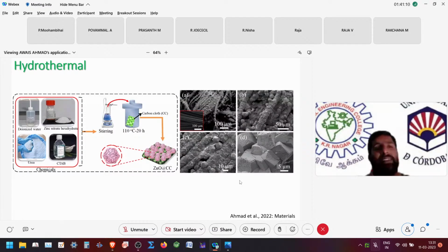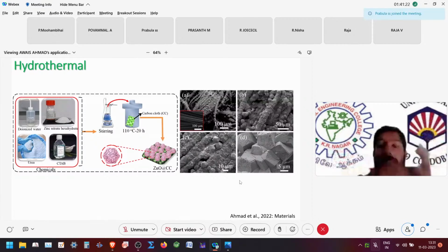So first of all is hydrothermal. As from the words, it comes true that hydro means water, thermal means heat. So what we will do is a reaction with water and heat, and then we put our precursor. Here we put zinc nitrate hexahydrate with CTAB and urea, and then we put a carbon cloth and did it in the autoclave with the appropriate time and heating, and at the end we get zinc oxide carbon cloth nanocubes.